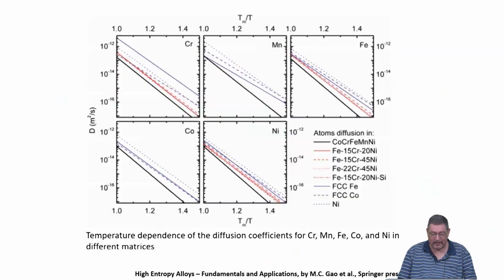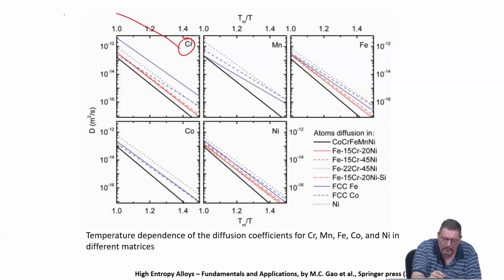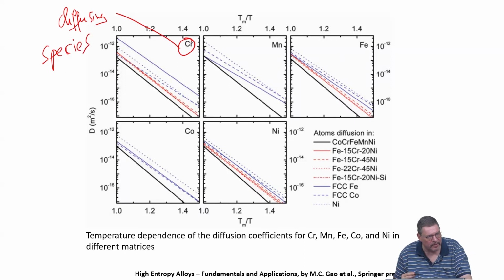We need to compare. They have done this, and this is shown here. So these are the constituent diffusivities derived from an interdiffusion experiment, and then compared to, so this is always the diffusing atoms. And this chromium atom, for example, its interdiffusion was measured in different matrices, so in different host materials. So the question the experiment answers is how fast is chromium diffusing in nickel, in FCC cobalt, in FCC iron, and in these alloys, and then it is compared to the high entropy system. And this is done for all 5 elements.